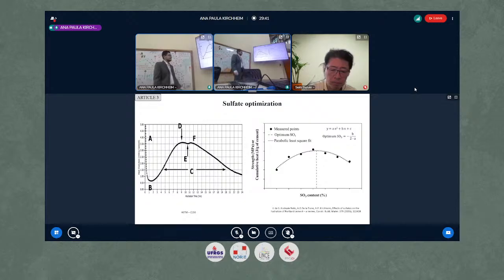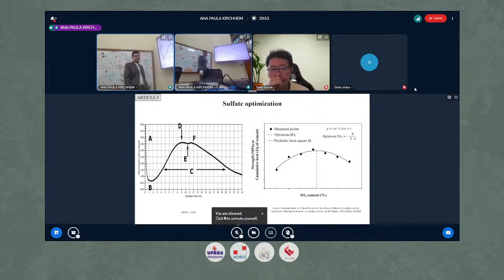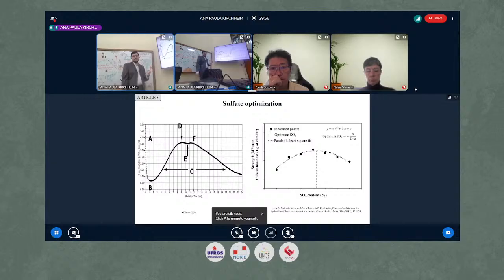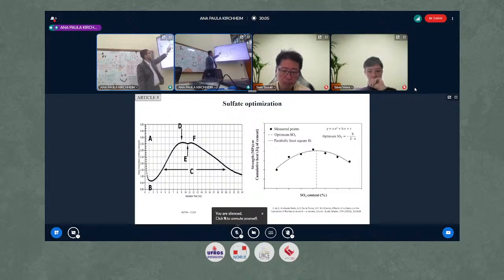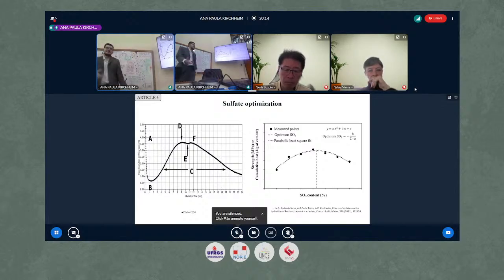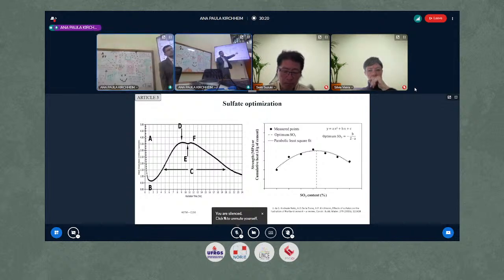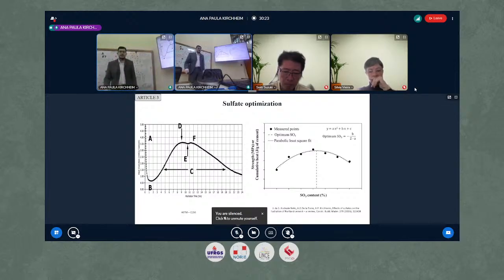after. So just to explain how we can optimize sulfates, there is an ASTM C1679 that explains this method. We can do it in different ways, but in terms of calorimetry, we can analyze the heat flow curve, and we want to see that the shoulder peak is a few hours after the main silicate peak, or we can plot the different total heat at 24, 48, 72 hours, and see the one that releases more heat. The one that releases more heat is the optimal sulfate content.